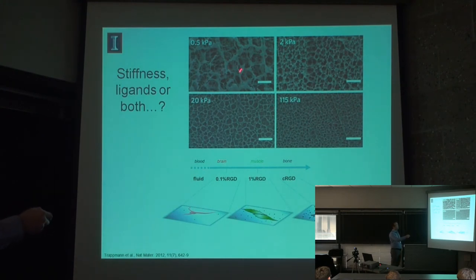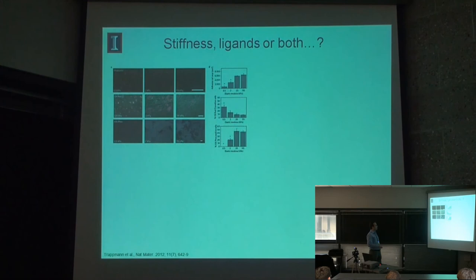It's going to see a very different distribution of protein depending on what surface it's sitting on because of this porosity effect. And so I think this is interesting in light of the result that we found, that by varying the spacing of these RGD peptides, you can vary the differentiation outcome. And so this may clearly play a role. And so this is the result that they found.